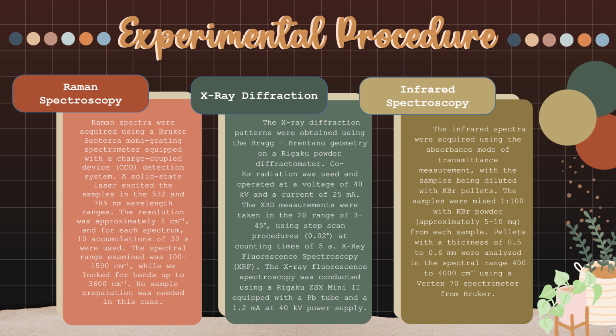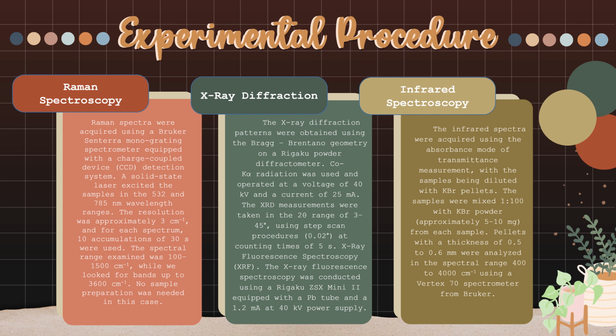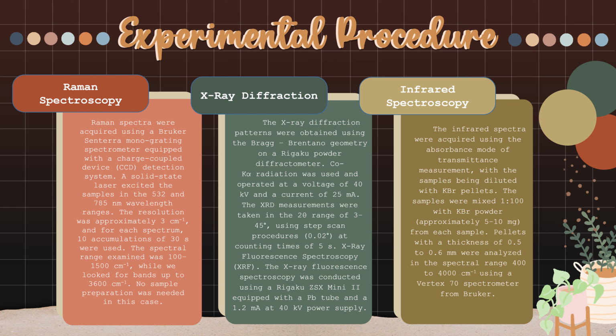In infrared spectroscopy, the samples were mixed in a ratio of 1:100 with KBr powder, approximately 5 to 10 milligrams from each sample. Pellets with a thickness of 0.5 to 0.6 millimeter were analyzed in the spectral range of 400 to 4,000 inverse centimeters using a Vertex 70 spectrometer from Bruker.